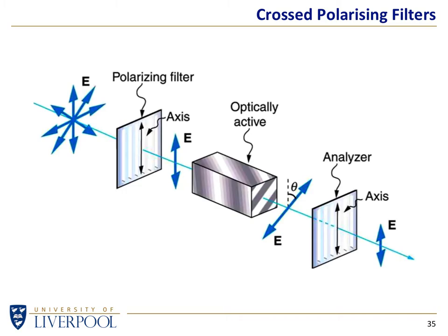And the amount of light that gets through depends on how much it's changed, in other words, how thick this material is, hence the different thicknesses of sellotape, each of which give a slightly different rotation of the polarization, and light of a particular wavelength will be rotated by a certain amount and will result in certain colors being present for certain thicknesses of the sellotape.